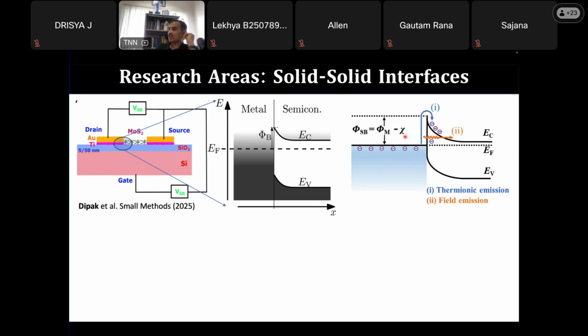And according to the Schottky-Mott relation, the Schottky barrier height is phi m, the work function of the metal, minus the electron affinity, or the ionization potential, depending on whether it's an n-type material or p-type material. And this is the same with holes also. This is for an n-type material, that's why I said chi, electron affinity. So now, in principle, the electron has to climb this barrier and cross it. The electron can also tunnel through it.